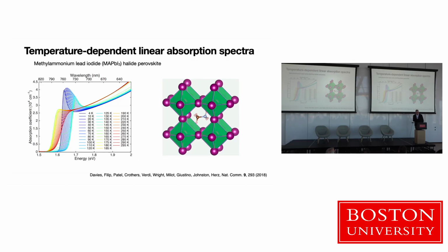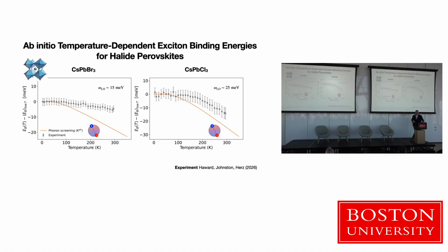So finally, I wanted to come back to the halide perovskite for a second, and show you another benchmark, if you like, to compare the physics I'm describing with some experimental data. This is an optical absorption spectrum for halide perovskite. The red curves are at high temperature, and the blue curves are at low temperature. This is an experiment done by this Oxford team. With this data set, one can fit the data, extract exciton binding energies, and plot that as a function of temperature. That's what the gray data are.